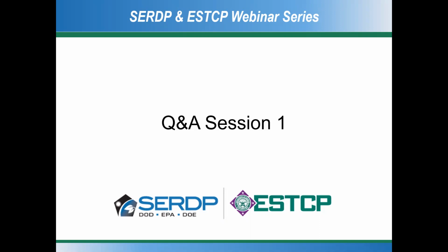Thank you, Liz. A question from the Resident Corporation. How thick on average are the coatings in question, and how often are they cleaned? Okay, so the anti-fouling paint systems that are applied to the larger Navy ships, that have a need to go 8, 10, and possibly up to 12 years between dry docking, those are 5-coat paint systems. The first 2 coats are epoxy anti-corrosive paint, and then the next 3 coats are the ablative anti-fouling. These requirements can be found in our performance specification, which is MIL-PRF-24647E, and that's publicly available for you to look up.